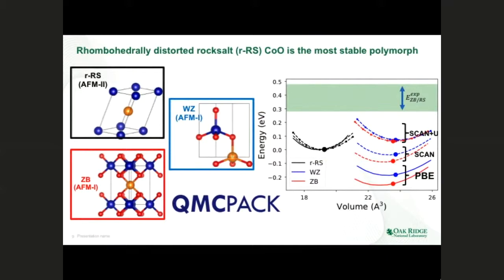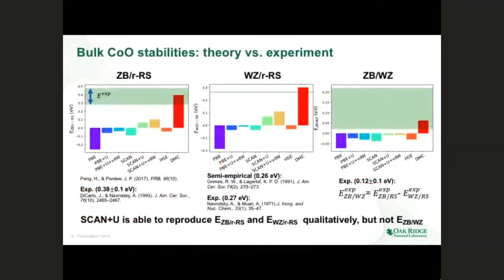And that's not even exactly reproducing the difference between the zinc blende and wurtzite structures, which I'll come to in a second. So here is the breakdown of all the energy differences between the 3 different compounds, and we are seeing that the green regions in here are the experimental energy differences between different compounds, and the red bar in here denotes the DMC calculations. So far, in all the 3 different compounds that I've studied, we can see that the DMC is actually the only method that can reproduce the energy difference between the 3 polymorphs exactly. And we can see that none of the DFT functionals are here able to get even the qualitative energy difference between the zinc blende and wurtzite structures.